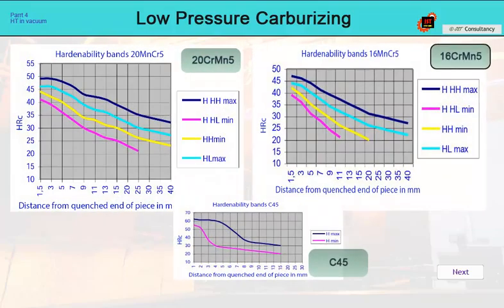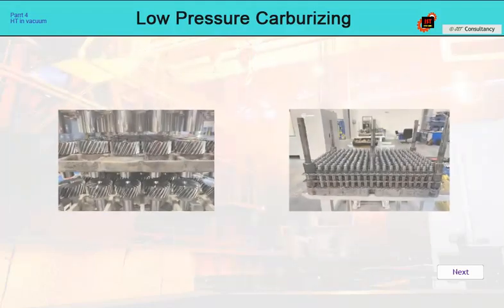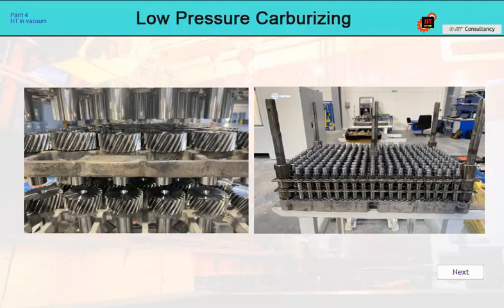We also have to consider the requirement for strength or hardness in the core. This is related to hardenability and hardenability bands. Small, tiny parts will work out fine, but there will be a problem with large parts. For example, with parts made of 16MnCr5 or 20MnCr5 steel, we will be successful with hardenability up to a diameter of 20 millimeters. Above this size, the results will be uncertain. We will have a hard carburizing layer, but the core will be soft.